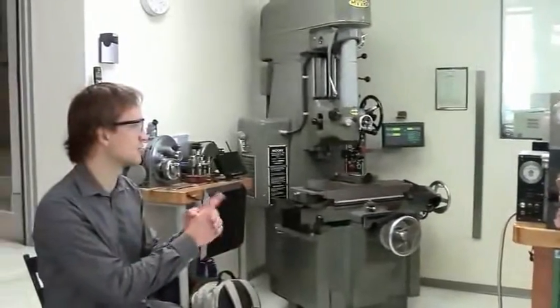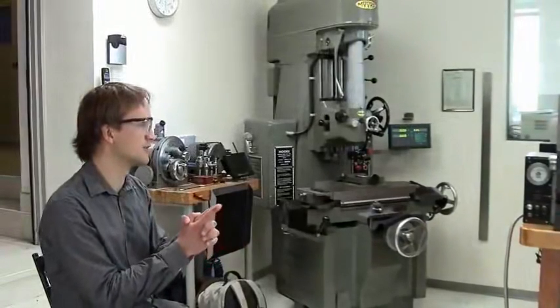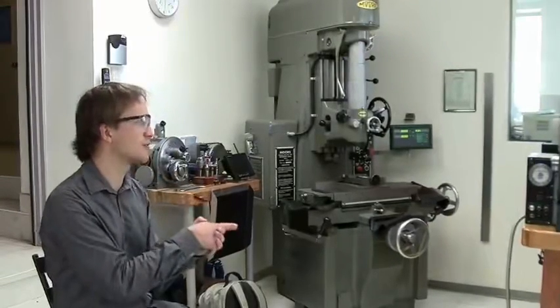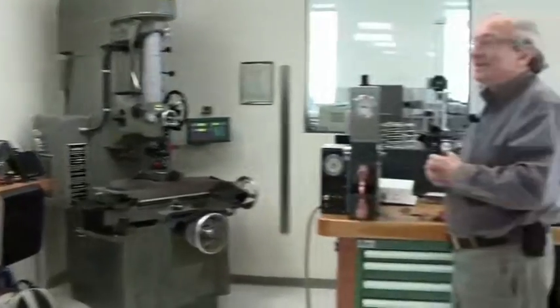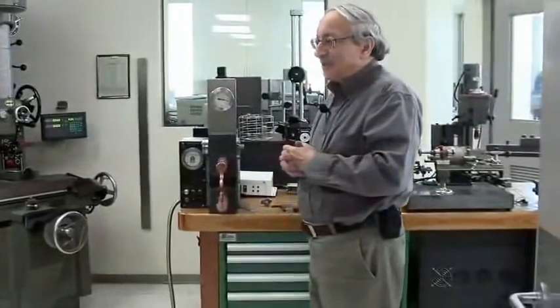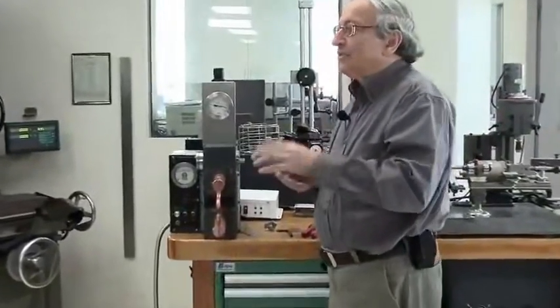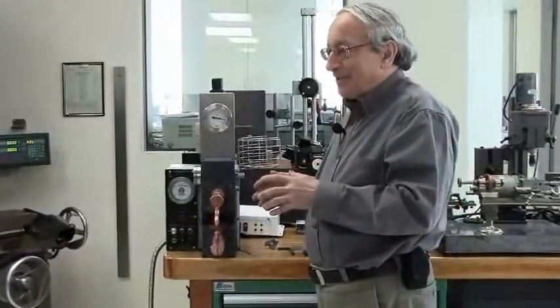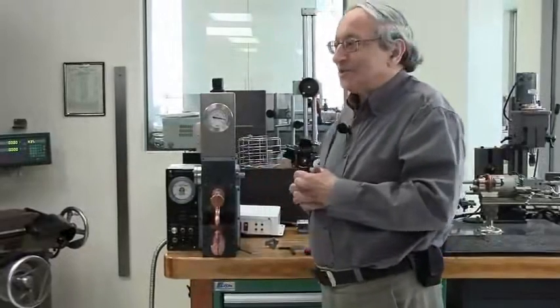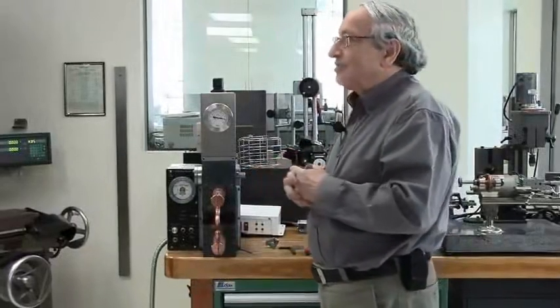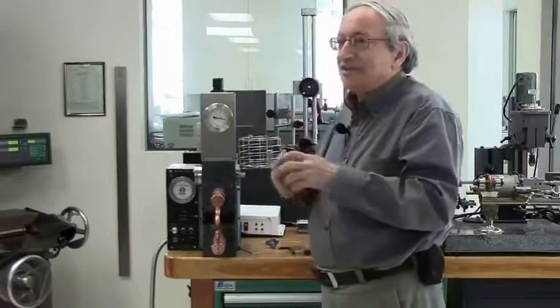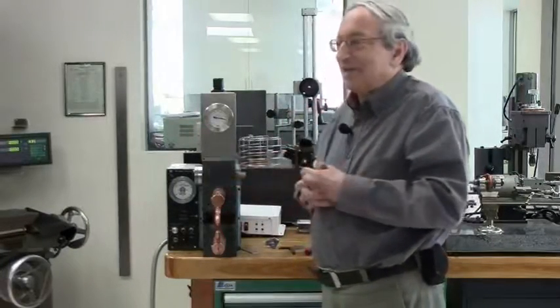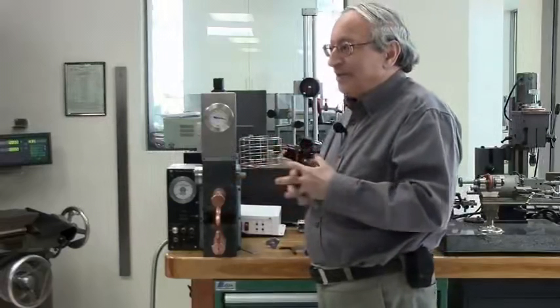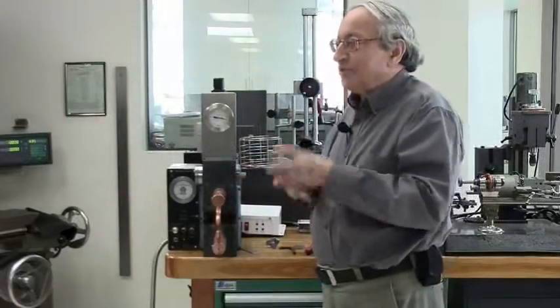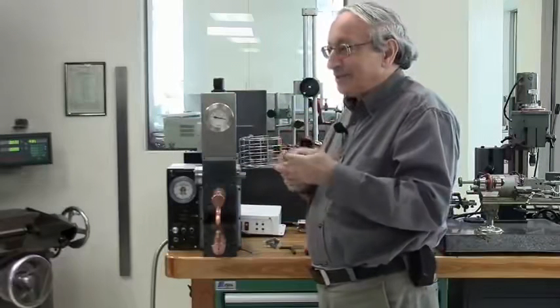If you have a spot welder that has both adjustable current and time, do you want to be adjusting the current to get different welds? Very good question. You always set it for the top current and always adjust the time, unless the lowest time setting is still too high, and then you lower the current. Because there is no advantage in adjustable current at all, because the faster the current, the less heat escapes sideways, so the less energy you need to do a weld. For example, a laser welder is super short times, and it has beautiful welds just because of that.